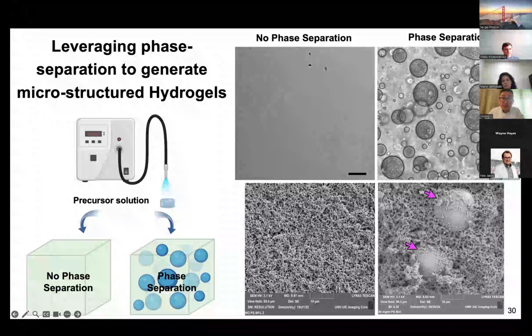In the non-phase separated gels, you can see there's no defined structures. In the phase separated gels, you have these nice droplets, domains that form in these materials. And then the SEM of the non-phase separated gels features these nanoporosities. And then in the second part, which is the phase separated gels, you have these defined particles that are